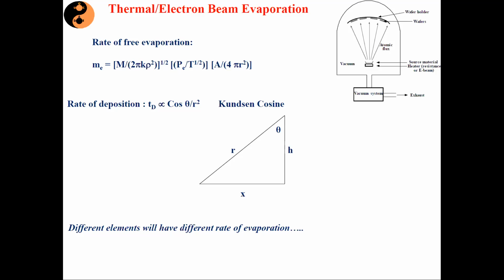Okay. Coming to another limitation of electron beam evaporation: suppose your target material is an insulator, then growing these materials with electron beam evaporation is not possible. The moment the electron beam interacts with your target, since your insulating material is non-conducting, the electron beam does not find a sufficient way of transferring its energy to the target material. Those electrons just reside on the surface of your target and form a space charge region, and hence it prohibits the deposition from taking place. And that is why these techniques are generally not used for insulators.